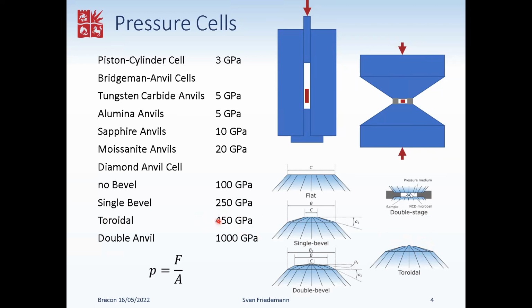And I'm going to say something about the sample spaces later on. Recent records have been achieved by putting double anvils. So that's using one set of diamond anvils to apply pressure, and then some nano-sized spheres of diamonds have been cut in half, and the two semispheres have been put on the opposing anvils, as it is shown in this sketch. And between the tips of those spheres, one can then achieve pressures up to 1,000 gigapascals. So that's the current limits in static pressure.